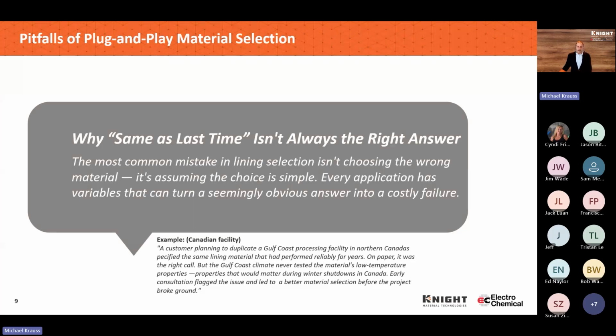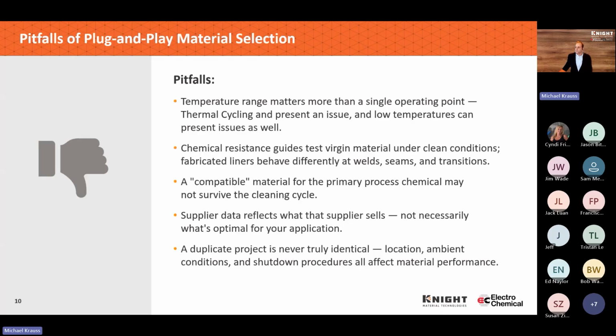The same type of thing happens frequently in chloralkali service, where the brine streams and feedstocks are different, and even operating temperatures, depending on recycle streams and process conditions, varying 5 or 10 degrees Fahrenheit, can make a big difference on whether one material works or doesn't. So understanding the history is really important, but just blindly moving forward with the same material because it's what you did in the past isn't necessarily the best situation.